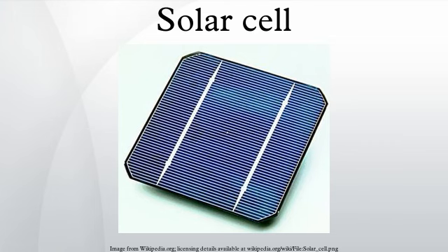Useful ions are most commonly found in the trivalent state. Er3+ ions have been the most used. Er3+ ions absorb solar radiation around 1.54 micrometers. Two Er3+ ions that have absorbed this radiation can interact with each other through an upconversion process. The excited ion emits light above the band gap that is absorbed by the solar cell and creates an additional electron-hole pair that can generate current. However, the increased efficiency was small. In addition, fluoroindate glasses have low phonon energy and have been proposed as a suitable matrix doped with Er3+ ions.